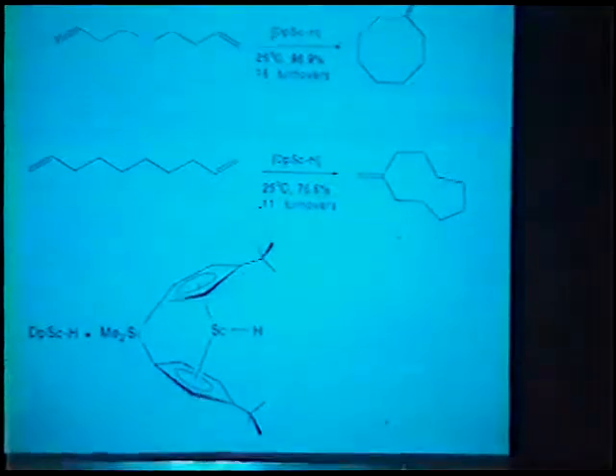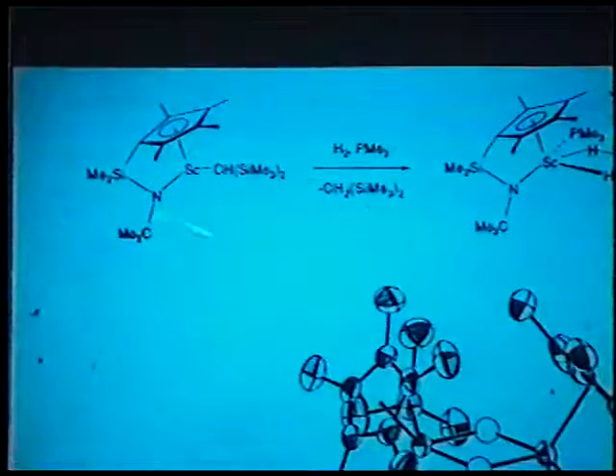We can think about coupling the two olefin centers together, that is, to examine alpha omega dienes, and indeed these cyclizations to the methylene cycloalkanes are, in many cases, remarkably effective. Okay. More recently, our group has been exploring even less crowded centers where we substituted one of the cyclopentadienyl groups by an amide, a tertiary phenylamide in this case. And here we can prepare hydrides of the type shown here, which can be crystallized and shown to have these electron-deficient bonding arrangements, much like diborane, or double hydride bridge supporting this kind of structure.